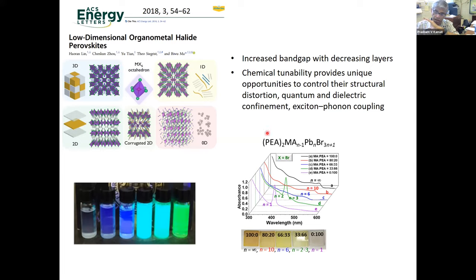So if you have 100% this PEA, you get a 2D structure. It's n equal to 1 because there is no methyl ammonium, so there is no 3D structure. So that is n equal to 1, which shows nice exciton absorption, shown here in the blue color. And then when you change the ratio of this methyl ammonium to PEA, you can tune n equal to 2, then 6, 10. So beyond 6, these films behave like a bulk material. They are not quantized structure. You can see the colors, you can study the properties. There is a lot of things going on.